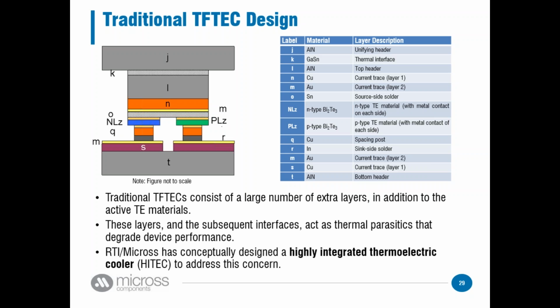But essentially, you have an active layer here, you have an active layer here, and you have a lot of structural components here. And that's just over time, as we've developed these thermoelectric devices, we've had these layers in there. The problem is, from a thermal standpoint, these are nothing but parasitics. These just get in the way. These just degrade the performance. And as you can see, all these layers, all we need is this and this from a thermal point of view to make it work.